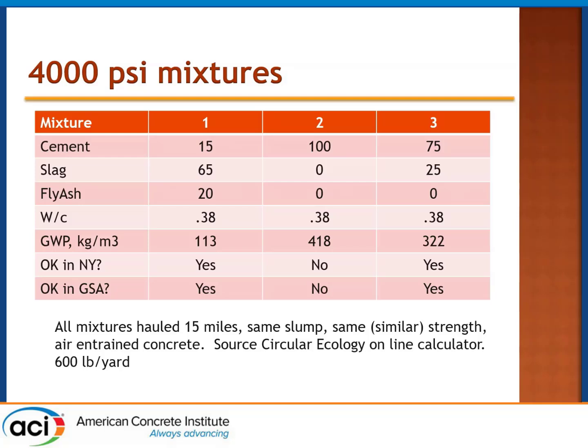The first mixture is 15% Portland cement by mass. It's wonderful stuff. It does not emit very much CO2, and if you cure it properly, then you're going to be just fine. The second mixture is a straight cement mixture, perhaps for a slab on grade, and the third one has a 25% slag replacement.